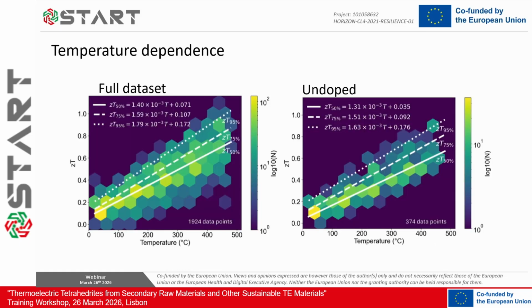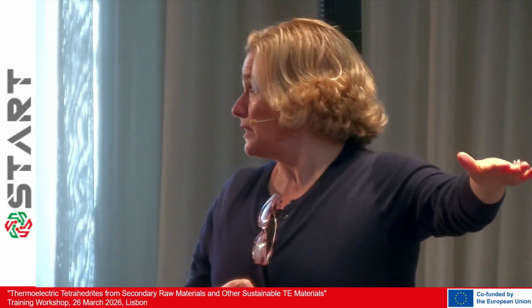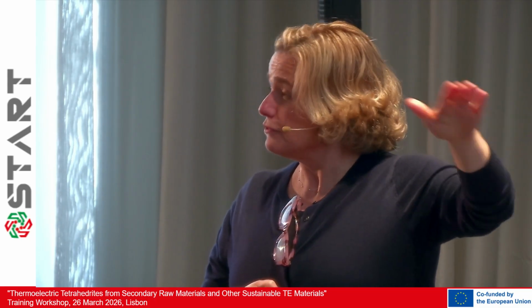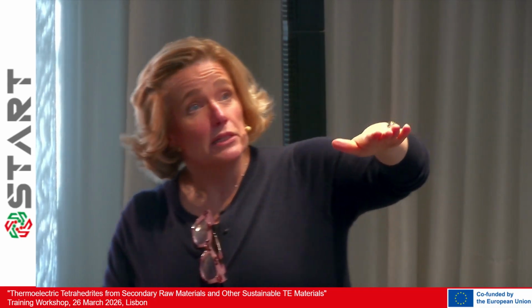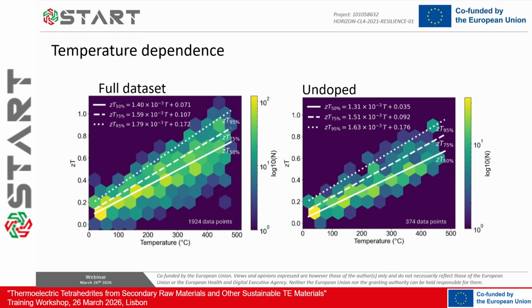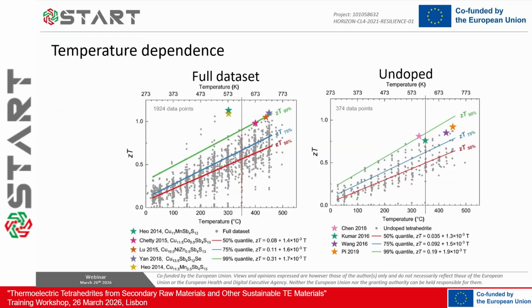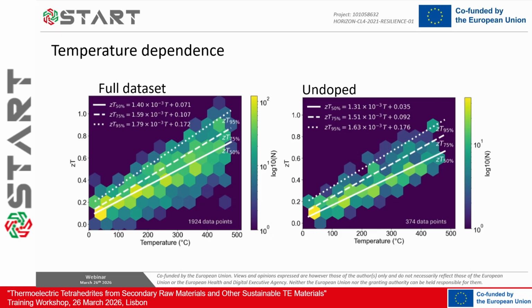If we try to separate, which is what we're doing here, we thought maybe this dispersion is because of the different chemical composition, so let's plot it for a single composition. The single composition with the most points is the undoped one. And you look at it, and it's also all over the place. You see a lot of zeros here, then values which are much higher. Of course you have worse statistics because there are fewer points, but still it's very messy.